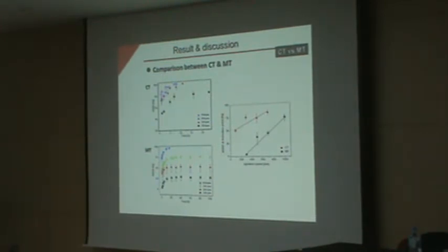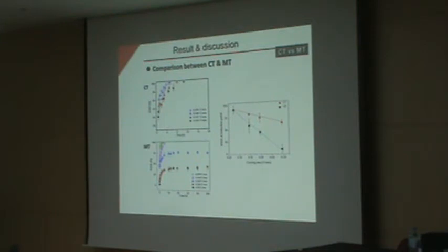In other cases, the initial CE just slightly increased and then kept at a constant value without further evolution. It is important to mention that the initial CE in both MT and CT increased with increasing rotation speed. However, the initial CE in CT is much higher than that in the MT crystallizer. The same result was found when varying the cooling rate.